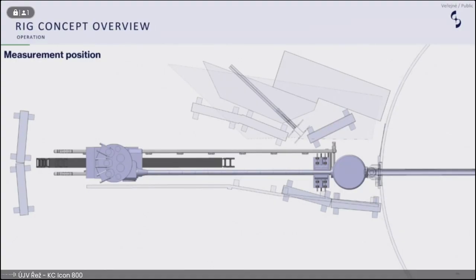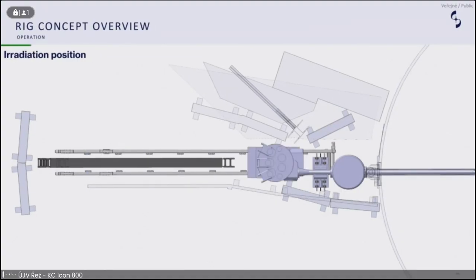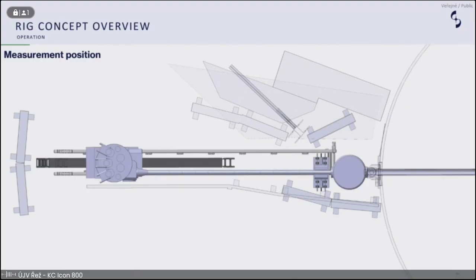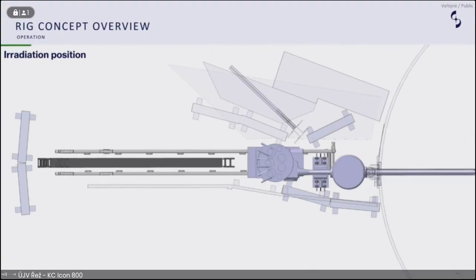Then we open the shutter, and we place our sample into the reactor. So we place it into that horizontal channel. We irradiate for a certain period of time. This is through calculations that we will collaborate with CDR on. And we will then remove that sample back out, close the shutter, turn the magnet on, critical current measurements taken, and then we will move back and forth several times during the irradiation campaign for those 28-30 days.